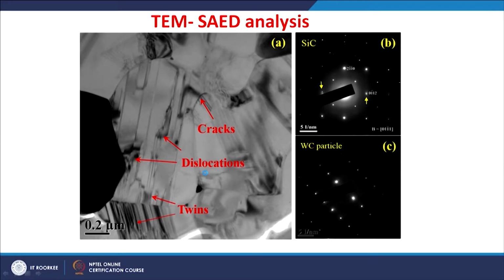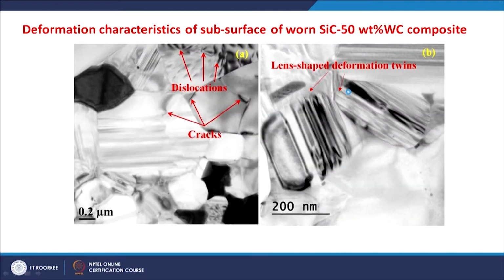Further, the selected area diffraction analysis also indicates the crystalline arrangement of the silicon carbide and the tungsten carbide particles. In addition to that, the regions underneath the worn surfaces show the signatures of cracks as well as dislocations. In addition to these dislocations and cracks, we can also see a lot of twins. The SAED pattern also indicates the presence of the twins. So, deformation is possible just below the worn region in terms of the dislocations as well as the twins.